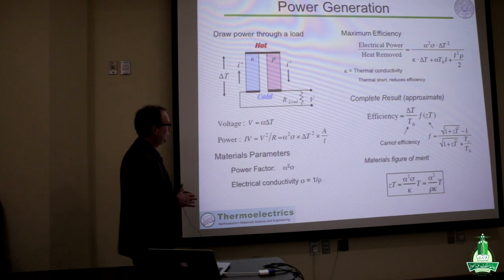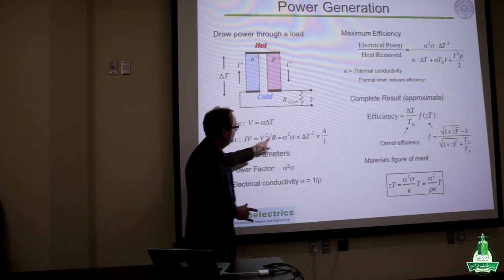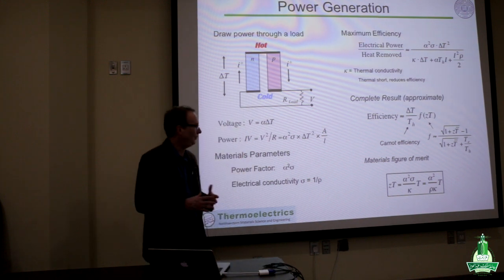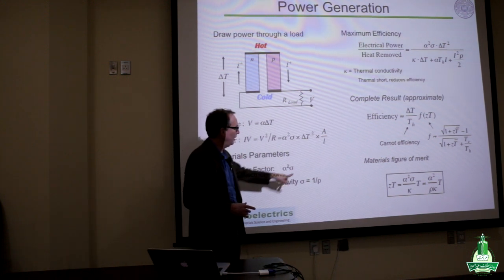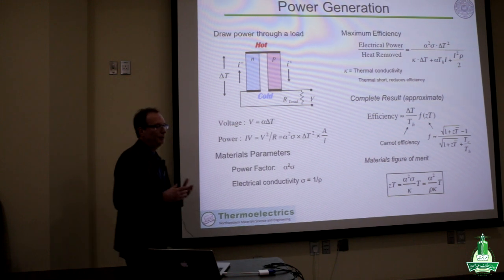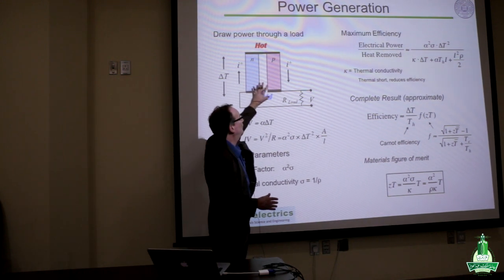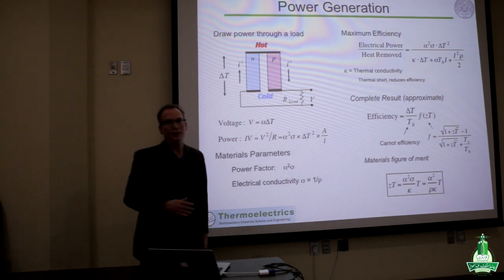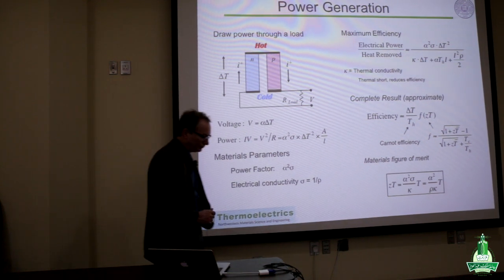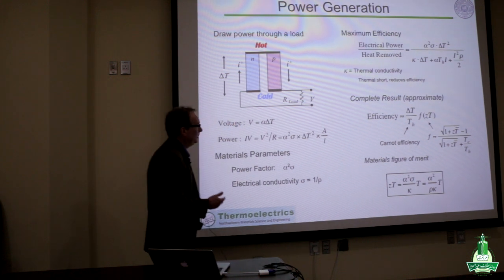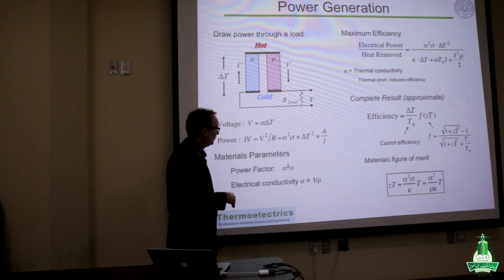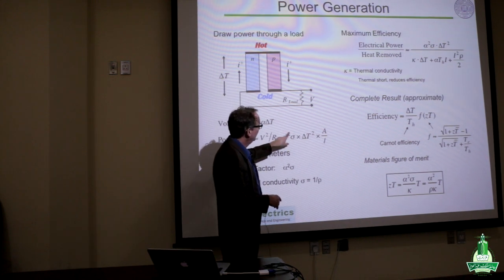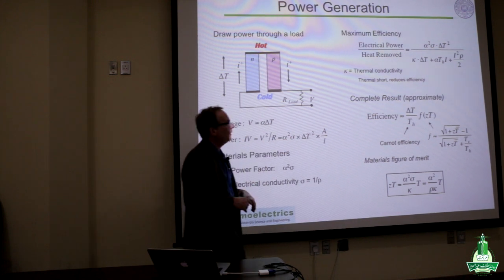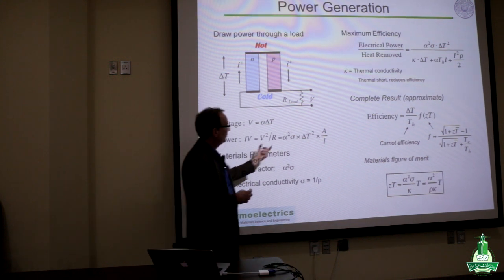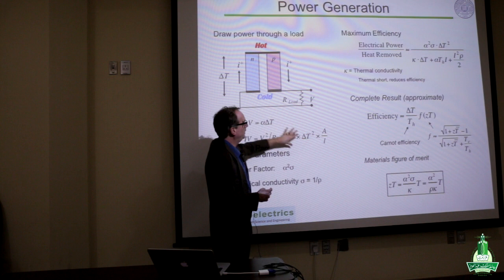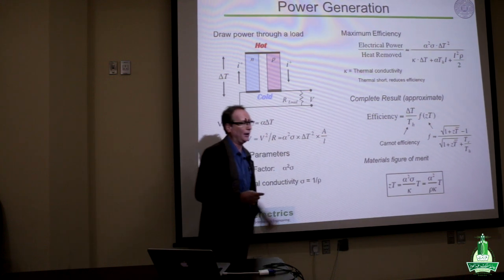But in terms of materials parameters, what we found is that the power depends on what we sometimes call the power factor, which is the Seebeck coefficient squared and electrical conductivity, as being the material parameters which help determine the power coming out of this system. Now, however, as we discussed this morning, to get power requires more than just considering the electrical power. We need to think about the system, because these parameters determine power as well.